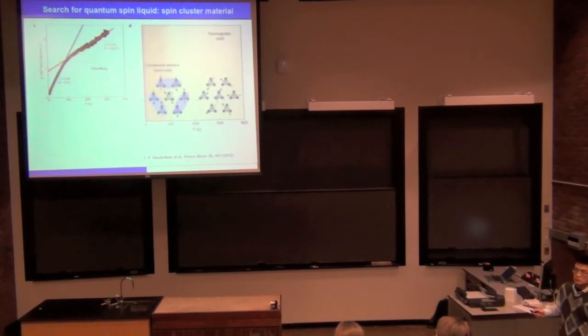And when we measured thermodynamic quantities, we find that this material does not show magnetic order down to very low temperature, 70 millikelvin in this case, although it shows a pretty big Curie-Weiss temperature. So the spin-spin interaction is strong. And if you look at the inverse susceptibility, there is a kink at about 100 Kelvin. And looking at the fitting coefficient, people realize that this material shows this interesting property.